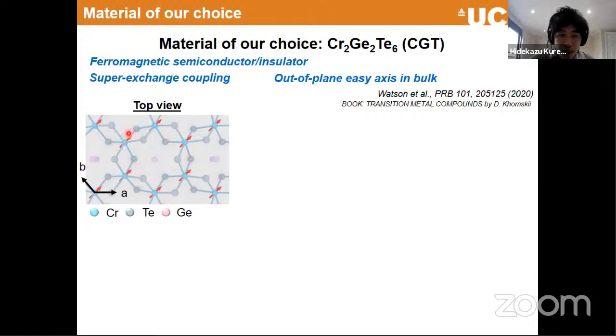And then between these two, there are tellurium atoms like that. So the magnetic coupling between these two chromium atoms is weak because the distance is too far. But it is possible to generate magnetic coupling through this tellurium atom. So that's what we call the superexchange interaction.